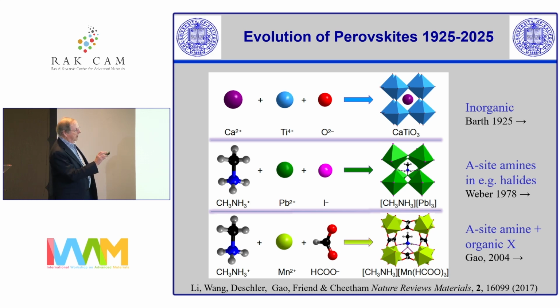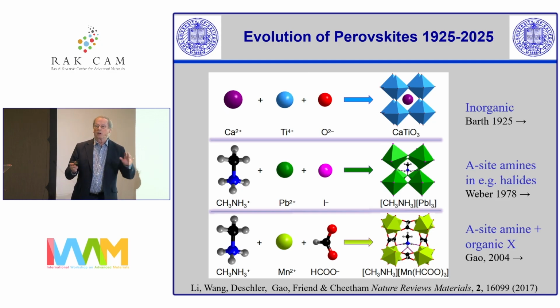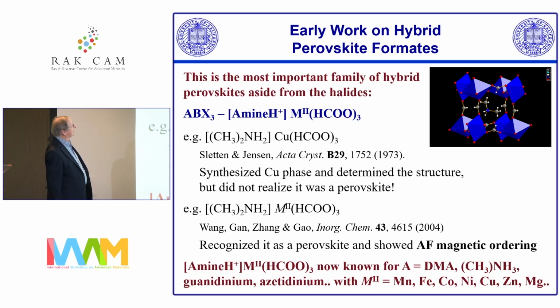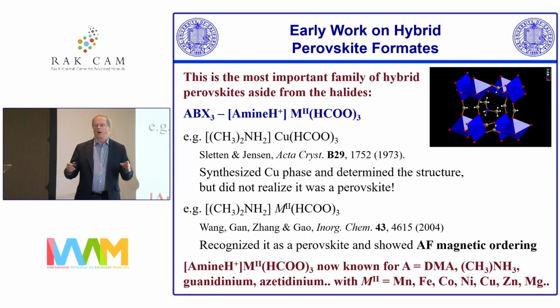You can also replace the oxygen in the perovskite. If you look at the oxygen bridge between the B cations, you can replace those with organic bridges, and in particular, the organic bridges based upon formate, the simple formate linker, bridging from one cation to the next, have been extremely important. And these, like everything else, have been known quite a long time, but were really highlighted by some work by Gao Song in 2004 in Beijing. And we worked on those when I was first in Santa Barbara, and then when I moved to Cambridge in 2007, we worked on those materials, and there's always something new to find, as we've seen throughout this meeting.